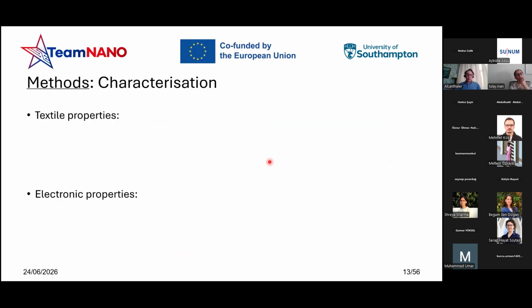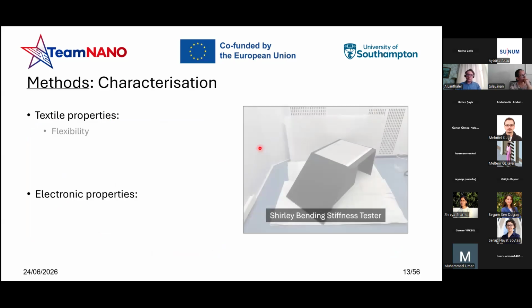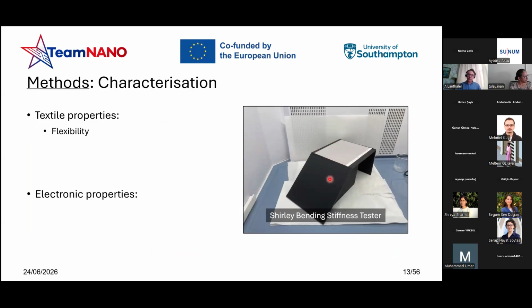So, to give you an idea of the methods, speaking about characterization, I divided it into two main fields. Having a look at the textile properties, for instance, we wanted to achieve flexibility and to check the flexibility of the textile itself before and after the electronic fabrication, taking advantage of this bending stiffness tester. It's very nice. The idea is to place a piece of textile over here on the top and push forward in order to bend it, and based on the total length of the textile until the very moment it touches the bent area of the tester, we are able to determine the stiffness of the textile through mathematical calculus.